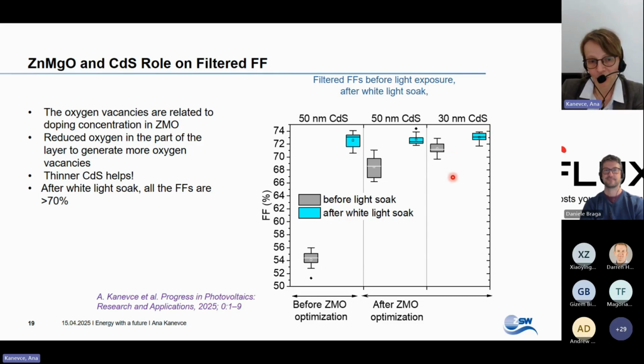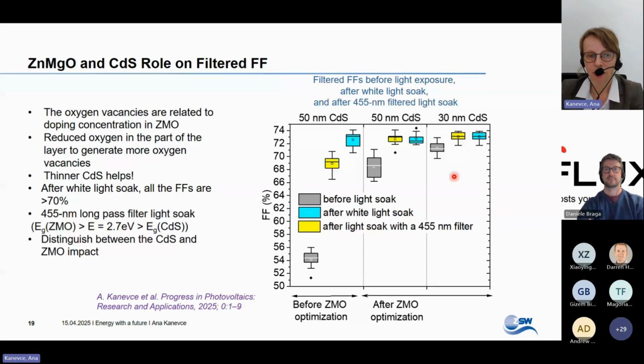There is an additional trick that one can do to play detective and figure out which layer is causing us problems, and this is to light soak with a long pass filter which has an energy between the band gaps of two materials. So we had a 455 nanometer filter. This has an energy of 2.7 electron volts, and this is larger than the band gap of cadmium sulfide, but lower than zinc magnesium oxide. Here are the results with yellow light, and then one sees that in this step, the zinc magnesium oxide problem is solved, and only cadmium sulfide is the problem.